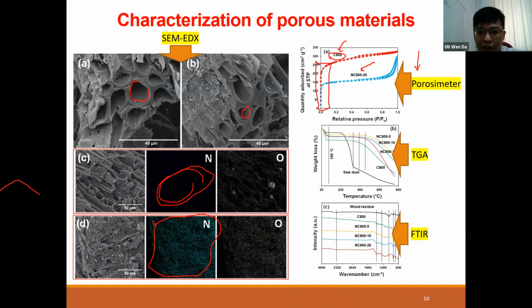For this kind of isotherm, if you have an initial very fast, rapid adsorption process below around 0.15, that one most likely corresponds to the micropores, within the smallest pores. And because C800 gives me a higher adsorption volume, I can straight away tell you that C800 contains a lot of micropores compared to the NC800.